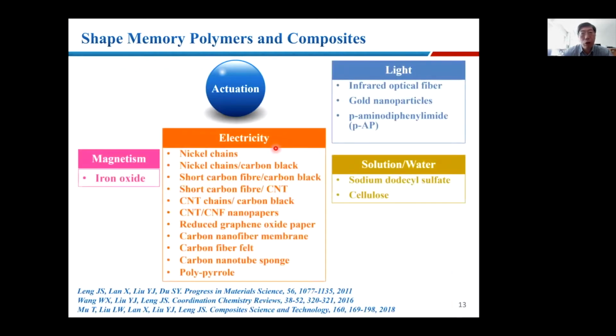So for actuation, as mentioned, you can simply make a conductivity network with different conductive particles like nickel, carbon black, carbon nanotube fiber, nanopapers, and also the nanotube sponge. For all of these, during heating, you have a conductivity network, then you can drive it, because you can heat this one above the transition temperature, then the material can change its shape. Then you can also do microwave, magnetism, light, and solutions.